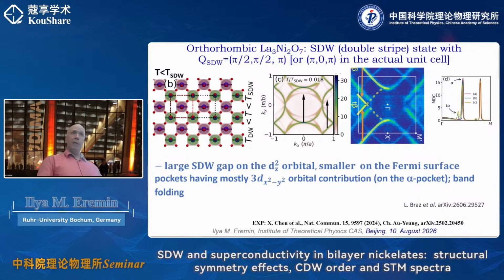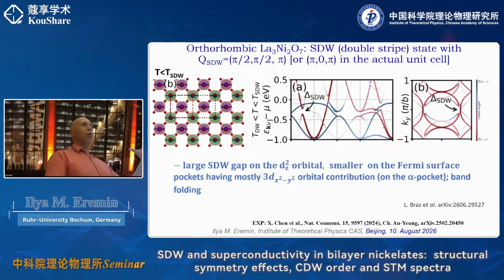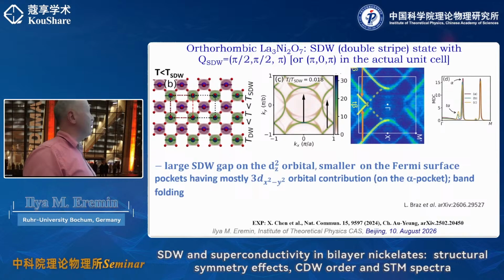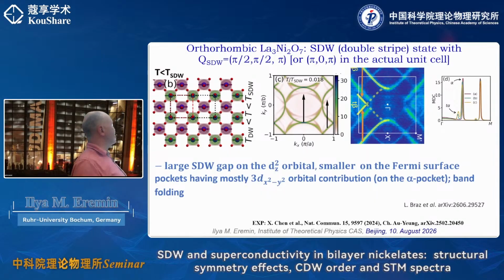But then there was another statement that they made. They said that the large gap they see is actually coming from the dx square minus y square orbitals. And that is something you need to take into account, that there is a true gap, and this gap is actually coming on the states which are not only at the Fermi level, and largely not at the Fermi level, because they sit on the dz square orbital. But of course, you do have effects for the x square minus y square pockets as well. And what is exactly happening is the following. In order to form a folded band, you need to take some spectral weight. So in other words, when you do this folding, some spectral weight, of course, has to be taken from here and from here.